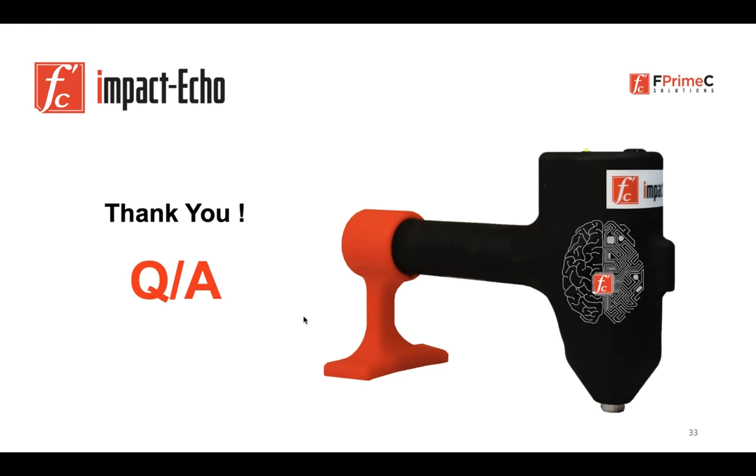Okay. And by your experience or research on this test, what is the minimum crack opening sensitivity that this test method could detect in millimeters? Yes, can impact echo measure a crack opening of less than a millimeter? As long as the interface of the crack is not interlocked, and even if there is a slight opening between them, less than a millimeter, impact echo can measure the depth of the crack.